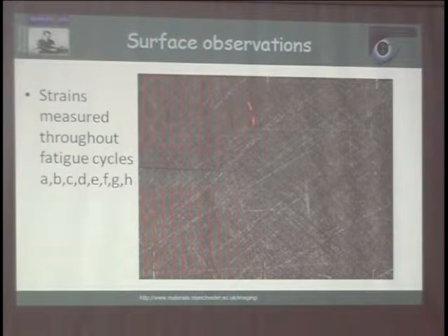I know it's not very easy to see, but hopefully you can see the red arrows here that are showing the opening at this point, and we measured it all the way through, from the initial constant fatigue through the overload event, through retardation, through acceleration, into retardation. So we measured at all those places.